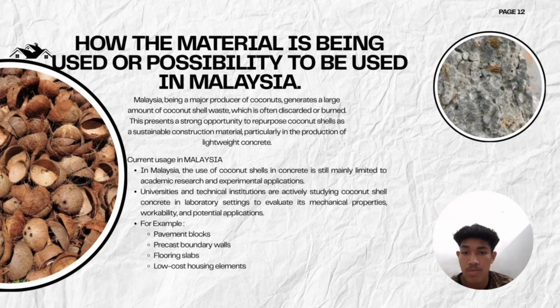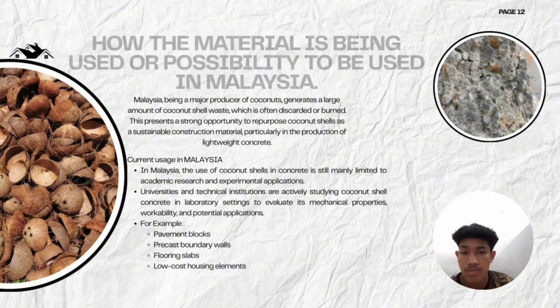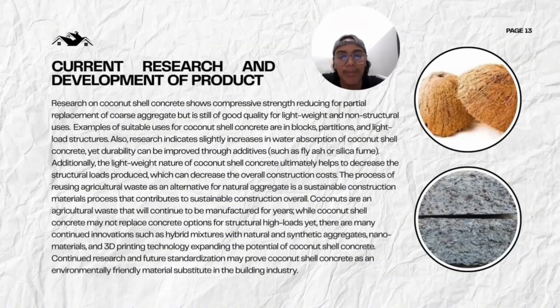The results show a clear trend. Increasing the percentage of coconut shell leads to a reduction in compressive strength. This is largely due to the lower density and different surface texture of coconut shell compared to natural aggregate like crushed stone.